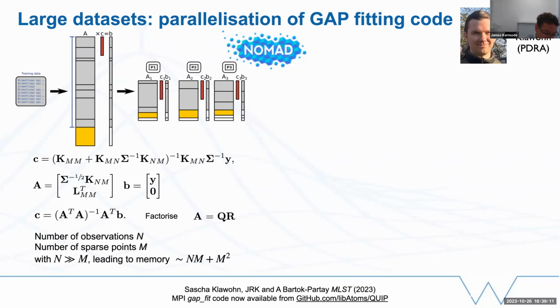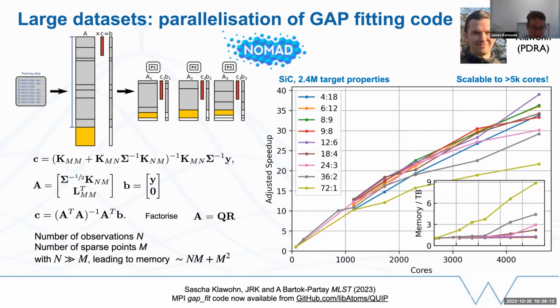And this actually works really well. It's really nice and scales up to several thousand cores. So this is work done within the Nomad project, and the code is now publicly available. It's merged and it's part of the QUIP GAP code. You can see it doesn't matter too much how you partition between MPI and OpenMP, so between threads and processes, providing you make a reasonable balance between the two, you can get really good scaling up to a few thousand cores and dramatically reduce the amount of memory that's required for the calculation.